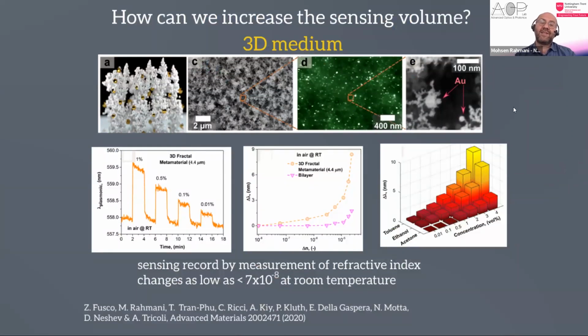And what we did next, we made it in a 3D fashion, because previously we had only plasmonic nanostructures on the bottom and this porous film on the top, and we had those nice results. So in this case, we went to the 3D fashion, and the plasmonic nanostructures, or gold nanoparticles, are distributed in the 3D way. As you see over here, it really enables us to detect 0.01% of gases, again as we did for toluene, ethanol, and acetone. You see that there are still different signatures for each of these gases, and indeed by this strategy we managed to detect 10⁻⁸.